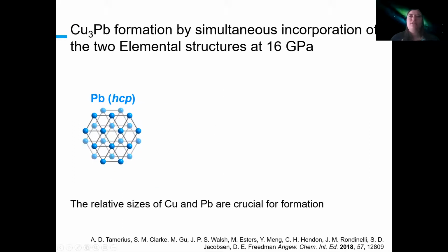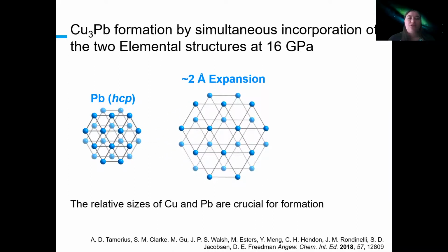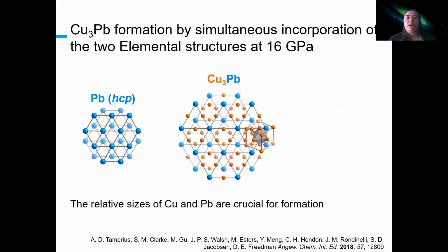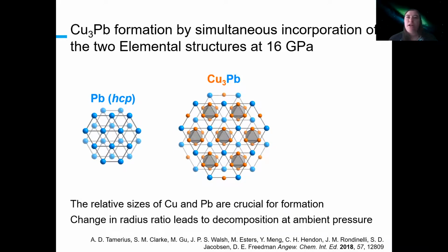And if we think about the formation of these compounds, what we see is if you start with the lead HCP lattice and you expand it by about 2 angstroms in the AB plane, you can stuff it with copper, and that copper can come from the octahedra in the FCC copper elemental structure. And so the relative sizes of these elements I discovered was really an important part of what's going on here.